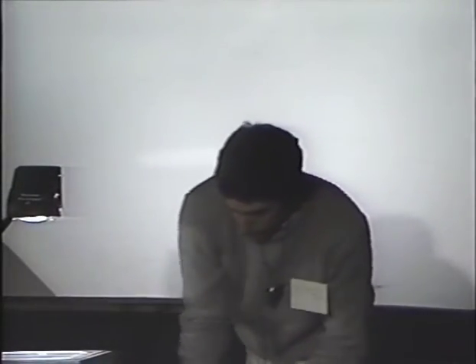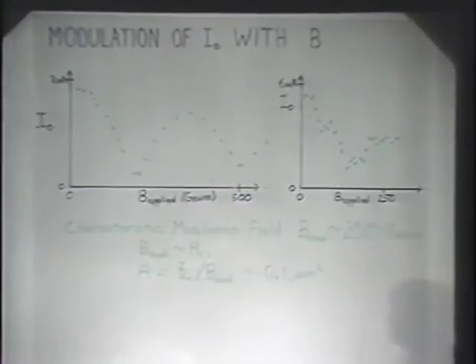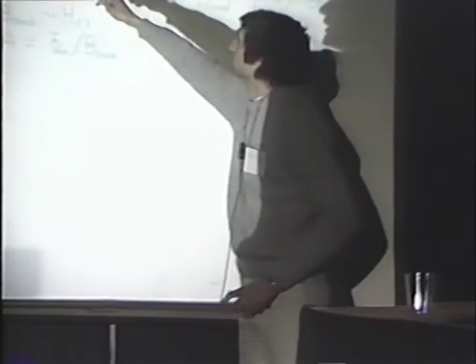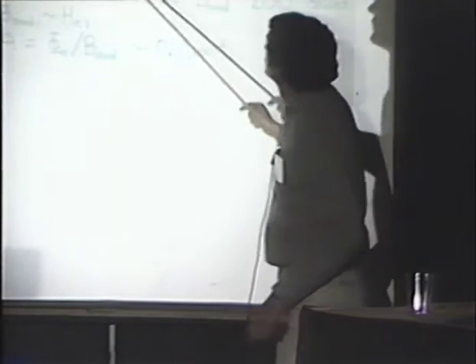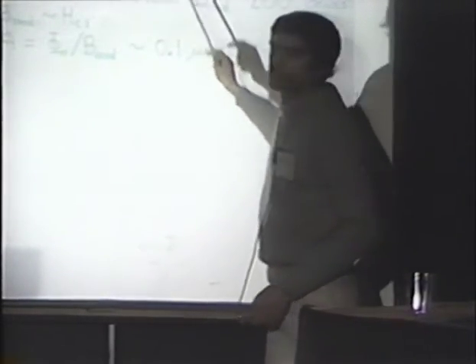We can put a magnetic field on the sample, and I plotted here the modulation of the critical current of these steps with applied magnetic field. We see a modulation pattern typical of a quantum interference device. This is sort of a good example. This is sort of a bad example where we see some complicated structure. The typical modulation field is around 200 Gauss, which is about HC1 in these materials.